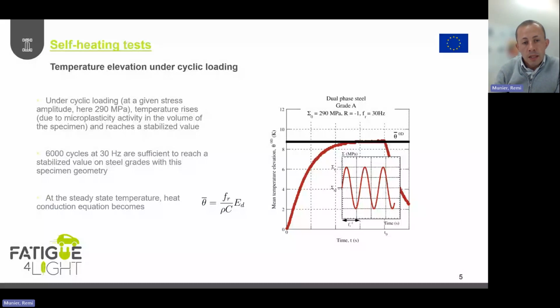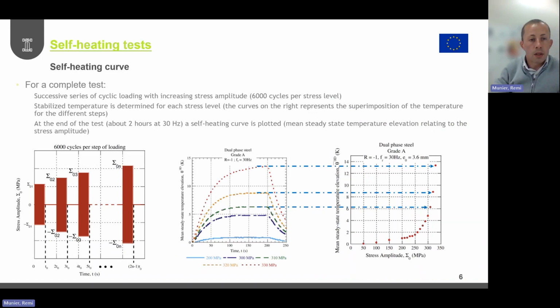Then the principle of the test under cyclic loading. Here you consider a cyclic loading at a given loading frequency, which is quite the same condition that Sergi is using for the stiffness method: a frequency of 30 Hz and a load ratio of -1. Then we can observe during cyclic loading a progressive elevation of the temperature up to a stabilized temperature, which is measured for each cycle. As for the stiffness method, there is a stepwise loading procedure with a progressive increase of the stress amplitude during cyclic loading, with successive series of cyclic loading and then unloading, just to permit the temperature to return to thermal equilibrium. For each series of cyclic loading, we measure the temperature evolution of the specimen. We can see here different steps of loading on the same specimen with the different evolutions.